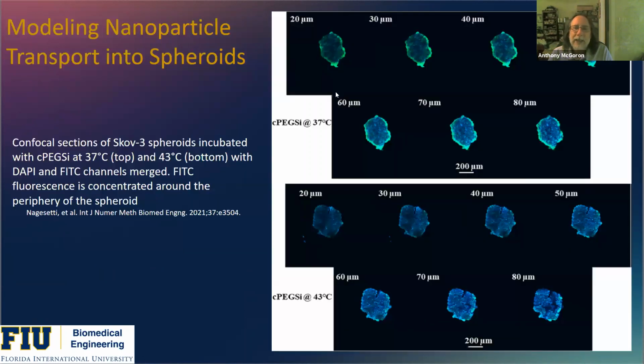So here we show uptake into a three-dimensional spheroid. These are confocal images of slices from the surface, 20 microns down from the surface, 30 microns, 40 microns, towards the center of the spheroid. These are 300 micron diameter spheroids. And at 37 degrees, we see the particles primarily associated around the outside rim of the spheroid. So they're not really diffusing into the spheroid. Whereas if we put these same spheroids in an incubator and expose them to 43 degrees, when we add the drug, we see a much more homogeneous distribution. The particles are able to penetrate deeper into the tissue, demonstrating the advantage of hyperthermia, at least on the distribution of the nanoparticles into the tumor.